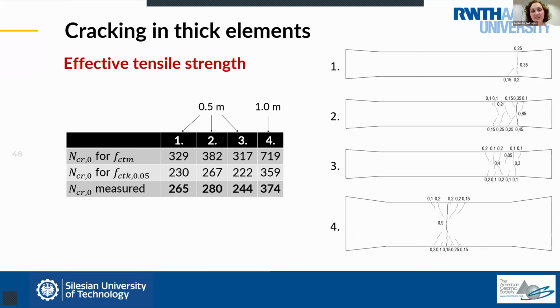Anyway, where I'm heading is that in the design, we should not focus on mean tensile strength, but rather on the characteristic or lower bound concrete strength, because these calculations show that to predict the cracking force, so the force that causes crack, we should take this characteristic value, so the lower value, because the crack will always appear in the weakest part. And moreover, especially focusing on the massive concrete structures, we see an important size effect. So when we consider an element which is of 1 meter thickness, the effective tensile strength, so the tensile strength reaching of which produces cracking, will decrease even further.